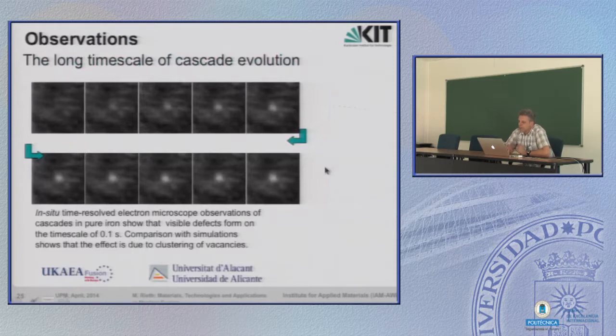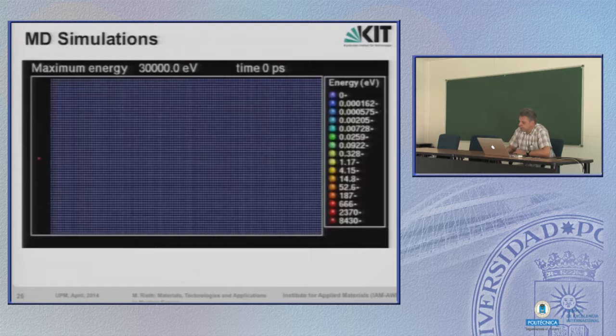This is the only source I have found where something like a cascade has been really observed in situ in a microscope. And you see here this bright dot appearing under the microscope, and this visible defect forms on a time scale of tenths of a second or so. So comparison with simulation shows that the effect is due to clustering of vacancies. We will see what this means. Anyway, the long time scale of cascade evolution is important.